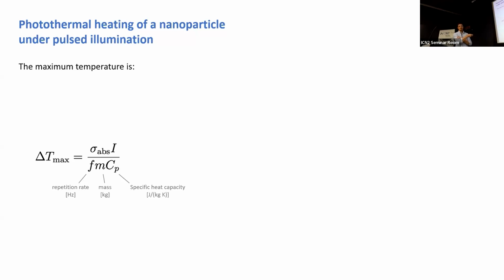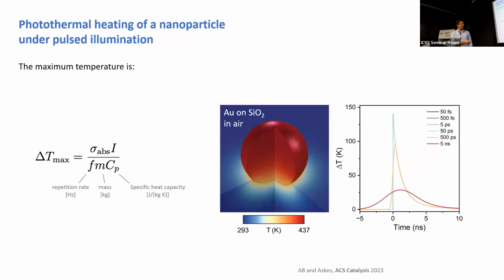But one thing that we can determine is how hot can we make it? Like, what is the maximum transient temperature increase? And now, again, it depends on the absorption cross-section and the irradiation, but there are other parameters that enter, in particular, the repetition rate, the mass of the particle, and the specific heat capacity. Now, if you plot this temperature profile, we did these calculations for a gold nanoparticle on silicon dioxide. This is a gold nanoparticle, 100 nanometer, and there is a little piece of glass. The nanoparticle is sitting a little bit inside the silicon dioxide, and there is air around it. And then we shine a laser pulse that is tuned to the plasmon resonance, and we vary the pulse length. Now, this is all calculations. So I say we shine a laser pulse, but it's just COMSOL, okay?